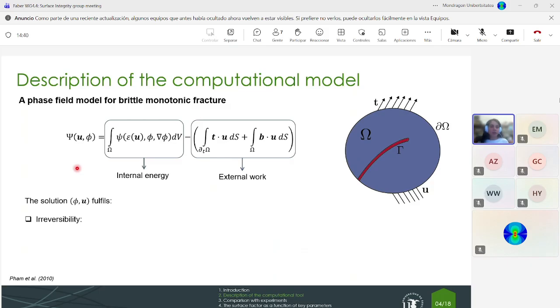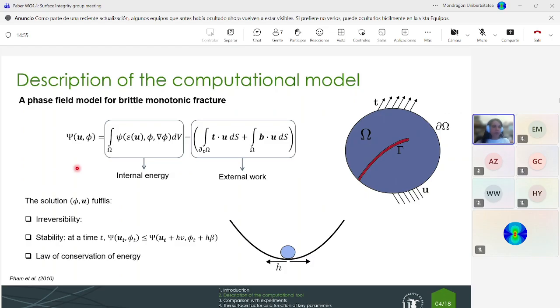First of all, the irreversibility. So the damage cannot come back, basically. The damage variable needs to grow in all the situations. Second one, the stability condition. That means that at each time, the energy needs to be as minimum as possible. And third, the law of conservation of energy. If we join together these three conditions, then we get the solution.